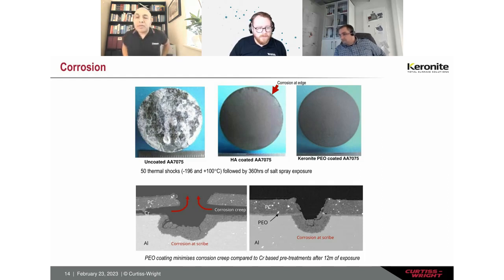Well, it is primarily given by the fact that the PEO coating goes through a number of those discharging events, leaving micro cracks and pores, very discrete pores and micro cracks. So just imagine that you have a crystalline matrix and some sort of amorphous phases within those cracks as well. So it's giving like a cobble effect, if you like. It allows you to flex. It's not a solid monolithic single-piece ceramic that just cracks if you put stresses on it. That is what is giving you the flexibility.